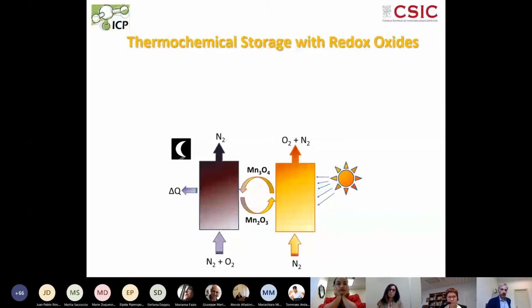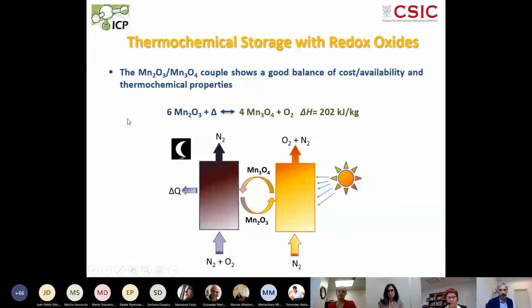So this is how the system works. We first have an inert gas, or even air in some cases, flowing through the system, and we have the heating of the sun, and we are going to release some oxygen. In this particular case, we are going to transform this oxide, the manganese Mn2O3, into manganese Mn3O4. And if we want to recover the heat, what we do is the opposite reaction, and then we provide the oxygen, which is taken by the solid and releases the heat. Well, if you want to see the chemical equation, it is that one. So we are changing, in this particular case, the manganese oxide Mn2O3 into the spinel, the Mn3O4, and we are